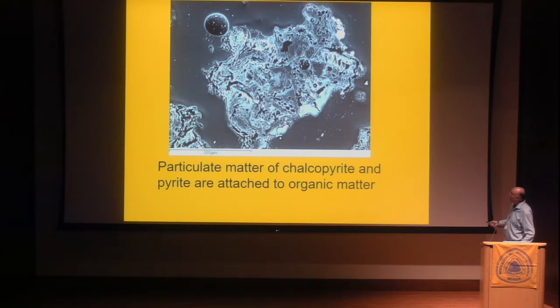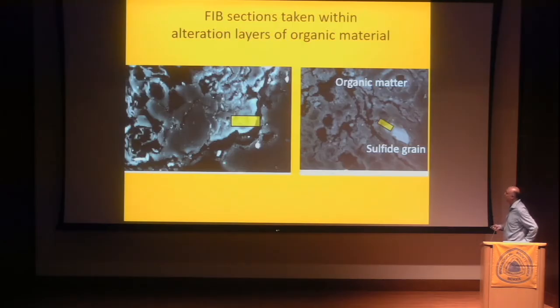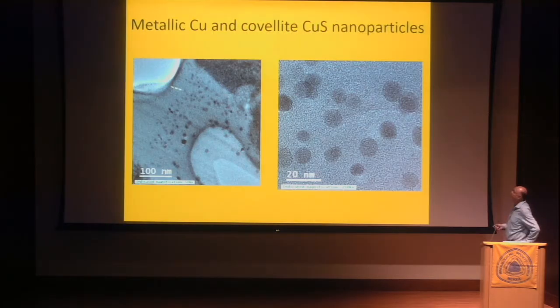And we decided we want to look now at the confinements within the organic matter. So we took two FIB sections, one along the outer surface of the organic matter, which is already bright here, and one where we have a chalcopyrite grain embedded in organic matter, and we looked here at the interface. And what we see is we find a lot of nanoparticles, very often metallic copper, shown here, metallic copper nanoparticles in the organic matter. And one is actually here, those are covellite nanoparticles.